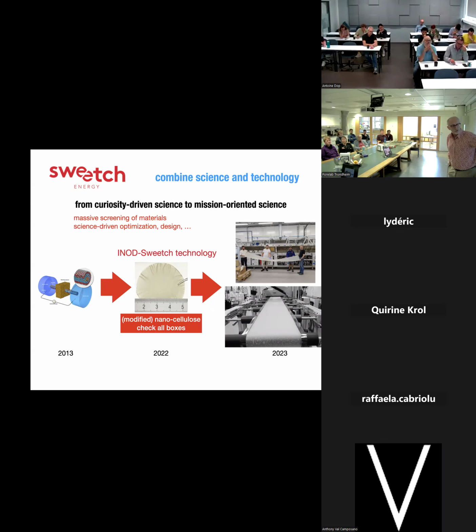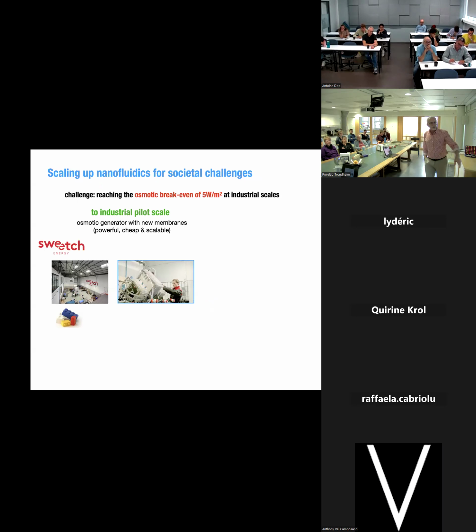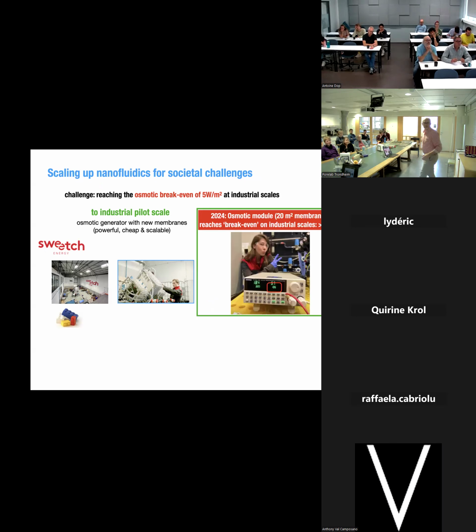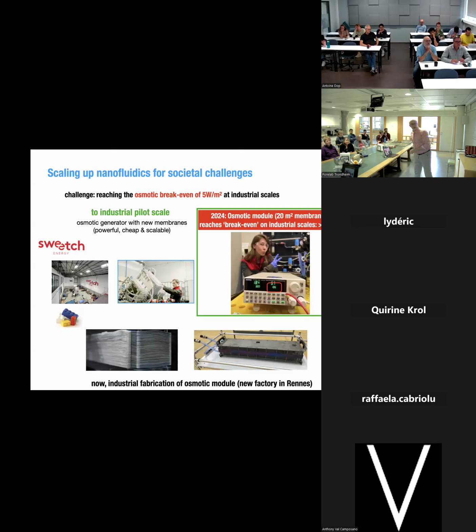And with this modified cellulose, which you see, this is in Finland, you can produce it by thousands or millions of square meters. They were able to develop it. Initially, instead of a single nanotube, this was this kind of osmotic cell. Now what's interesting is that last year, with their new materials, and you have to be careful also with the design, in a multi-layer system like that, which looks a bit like an LED, they were able to go above 6 watts per square meter.